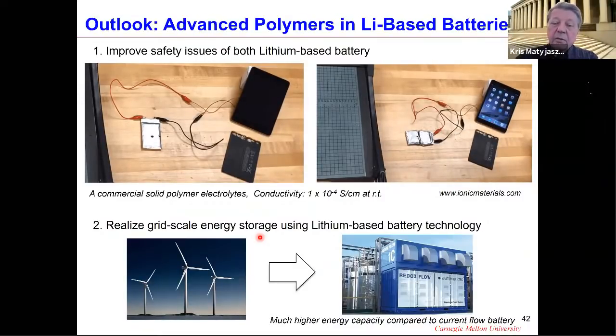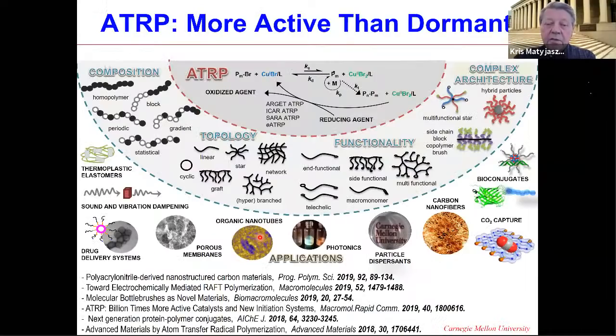So with that, I would like to summarize that ATRP, in fact, is much more active than dormant, although we always need these dormant species in order to equilibrate and extend the life of growing chains from seconds to hours. We developed new catalysts, which are very powerful. They can be used at very low concentrations, and you can use various reducing agents to regenerate and also stop them at any time you want to stop them.